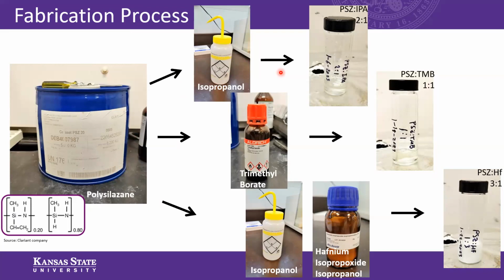Furthermore, trimethyl borate was used to produce SiBCN pre-ceramic liquid polymer. And finally, for SiHfCN pre-ceramic polymer, polysilazane, isopropanol, and hafnium isopropoxide isopropanol were mixed in the following ratio to achieve the ideal pre-ceramic liquid.